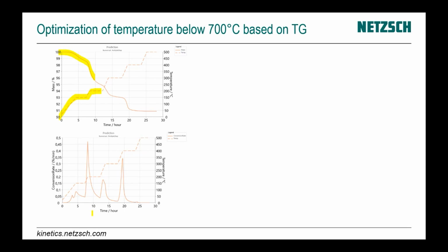The second picture is the first derivative of our simulated curve, or just a curve which happens during our production process. And now, if we would like to see how to optimize our production process, our industrial process, we can find firstly points where the reaction rate, the decomposition rate is the highest. So it means that these are the points where we lose quality. And we must additionally find the points where the reaction rate, the decomposition rate is too slow, so where we lose time.